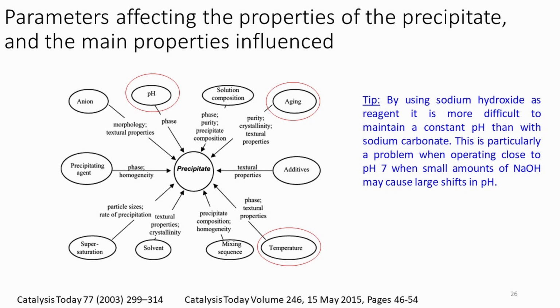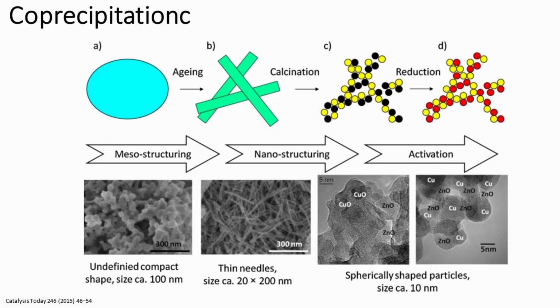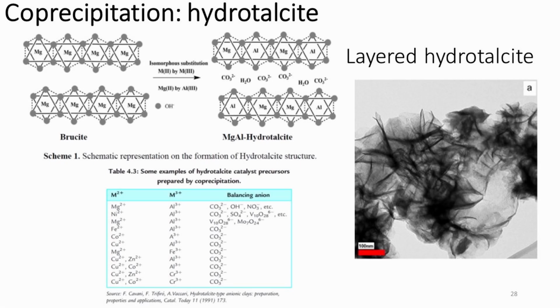All catalyst features, such as surface area of the active phase, pore structure, and particle size and shape, are strongly dependent on the process conditions, like the nature of the method, dosing of ingredients, mixing and stirring. These conditions have to be accurately controlled throughout the precipitation process. A complication is that probably no single condition exists that is optimal for all of the above processes.